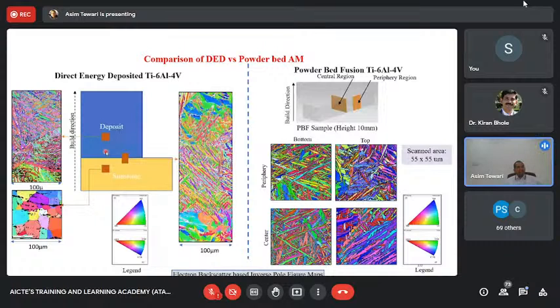One is the direct energy deposition, DED technology on the left-hand side, and the powder bed fusion technology on the right-hand side. We performed experiments on the same alloy for both DED as well as powder bed fusion, and we wanted to see how the microstructure looks. And this is how it looks. Of course, there's a substrate, and on top of the substrate we have the deposited material. The substrate has a slightly different microstructure from the deposited material, but the material has a somewhat similar structure, though the exact coarseness and other things would vary depending upon our process window.